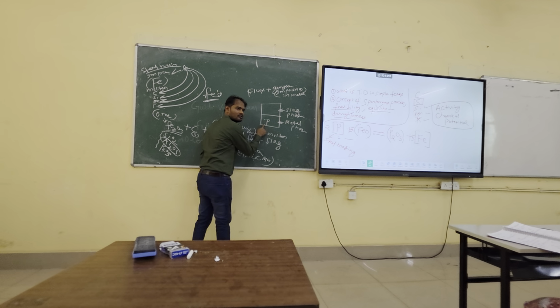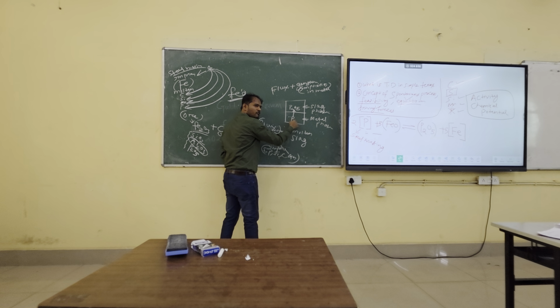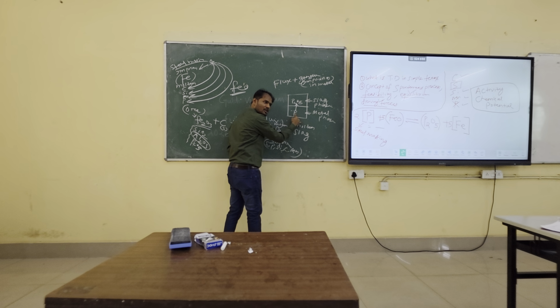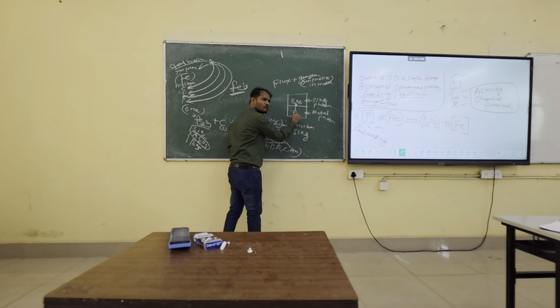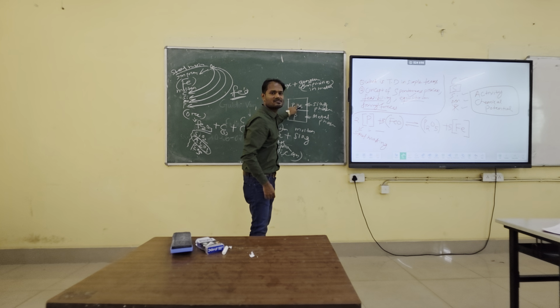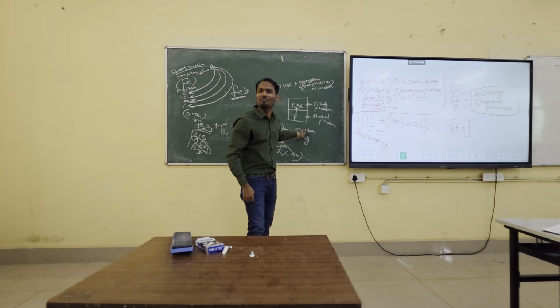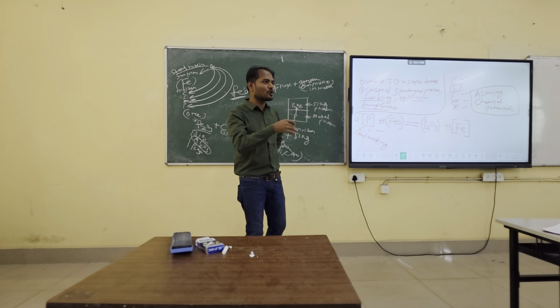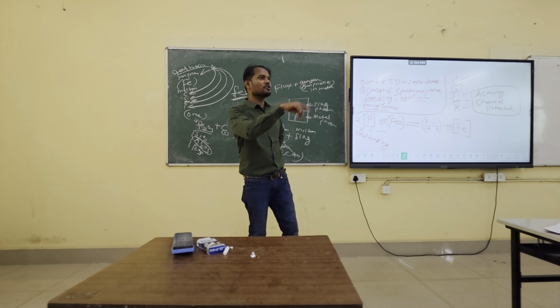Initially, phosphorus is here in the metal, and you want to send it to this phase, slag. You want to remove it, reduce it. It will become P2O5. So in other words, initially the activity of phosphorus was more in the metal, or the chemical potential of the phosphorus was more in the metal phase. That's why it is moving to the slag, so that the chemical potential or the activity can be reduced. But with time, what will happen? The more phosphorus is removed, the activity or chemical potential of phosphorus will again be higher in the slag phase, right? So again, it may come back to your metal, but you don't want that, no? You want to remove the phosphorus. You don't want your phosphorus to come back into the metal, into your steel.